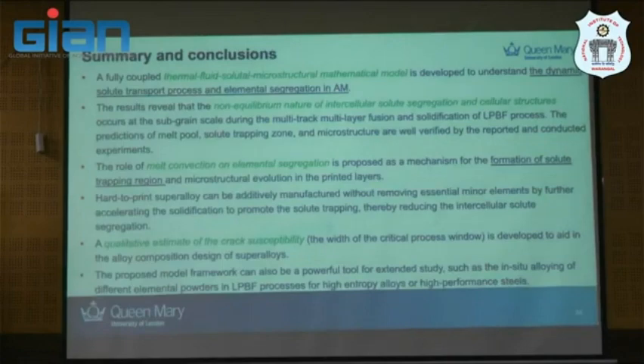In summary, I just want to say that the fully coupled thermofluid solute microstructural mathematical model is developed to understand dynamic solute transport and element segregation in AM. We revealed the non-equilibrium nature of intercellular solute segregation and cellular structure, which occur at the subgrain scale in the multi-track, multi-layer fusion and solidification of LPBF. The prediction of the melt-pool solute trapping zone microstructure is verified by available reported experiments. So we have used both literature and also a new set of experiments.